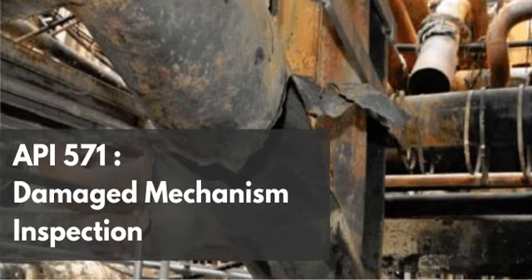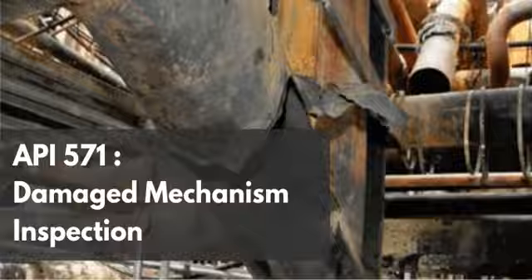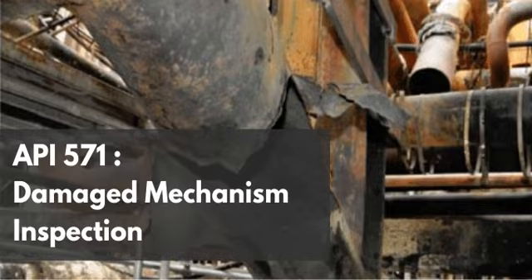Leaving the bare metal matrix completely naked and exposed to the high carbon gases. Exactly. No oxygen means no oxide shield. No shield at 1,100 degrees Fahrenheit means the carbon rushes right through the open doors of the lattice. So we have the bare metal, we are operating above 1,100 degrees, and the pipe is filled with high carbon gas. Let's talk about the speed of this invasion.